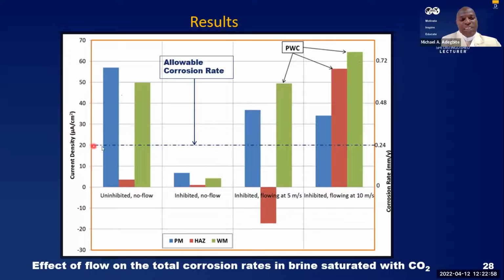And we can see the corrosion rate here has crashed for all the components across the entire weldment. It's crashed far below that. It means that the inhibitor here, in a no flow situation, is very, very effective. But how about when there is flow? This is in a no flow situation. That is, no movement. The inhibitor is very, very effective.